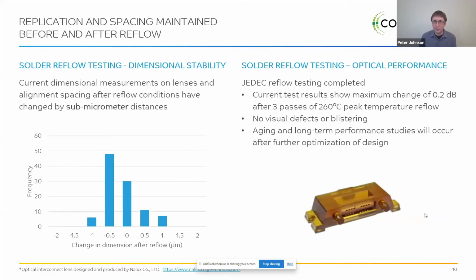The dimensional stability, how we were measuring it, was based on alignment spacing of these various different components. And this is just showing for 260 degrees C reflow, 3 passes, the dimensional change of these various, say, lens spaces, empty ferrule connection spaces, a variety of different conditions. And you can see they mostly change by less than a micron, which is a very good result for a resin to go from effectively room temperature to 260 and back over and over again, and it's still remaining dimensionally tolerant through all of those processes.